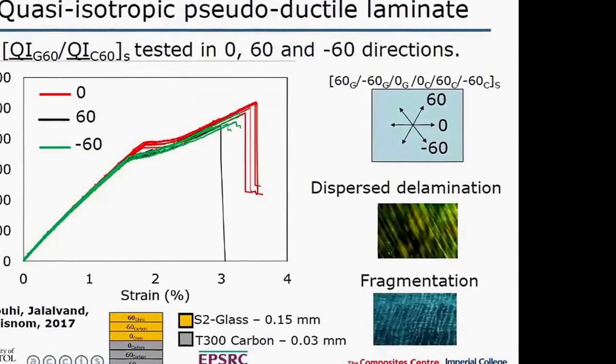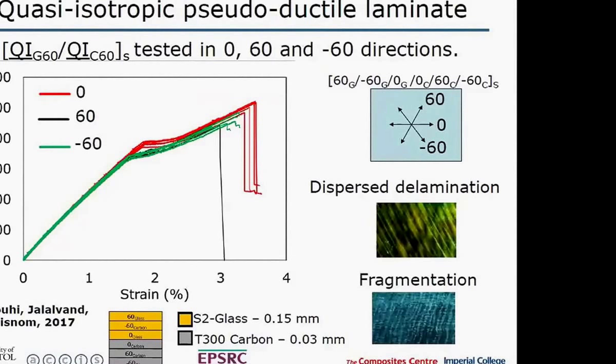So here we've got actually a 0/plus-minus 60 configuration where we've blocked the glass together. So we've got a block of glass, quasi-isotropic, a block of carbon. This glass is standard ply thickness, this carbon is thin-ply, and then we get the same sort of non-linearity with a bit of a plateau region here, similar to what we saw with the UD. So what we see with the unidirectional composite carries across to what we see in the quasi-isotropic. And it's interesting to see we can load it in any of the 3 directions and get a similar sort of response, although there is a bit of a difference between this red one, which is loaded in the 0 direction, and the ones which are loaded at 60 degrees.